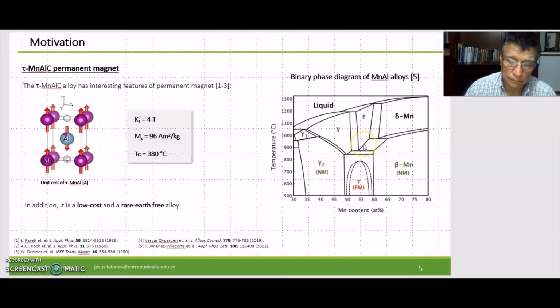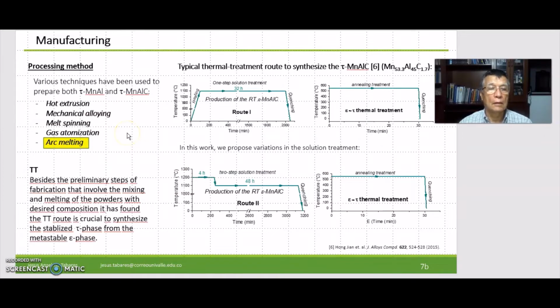quenched at room temperature. However, in this crystal transformation, some equilibrium phases such as beta manganese and gamma 2 aluminum 8 manganese 5 can appear and could deteriorate the magnetic properties of the ferromagnetic alloy. There are various techniques for the production of tau manganese aluminum carbon: hot extrusion, mechanical alloying, melt spinning, gas atomization, and arc melting. We are interested in using this technique for the production of our samples.